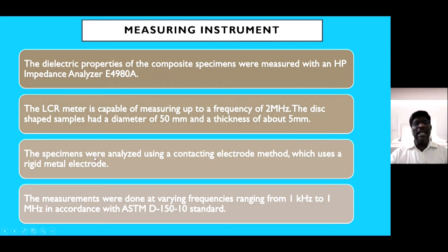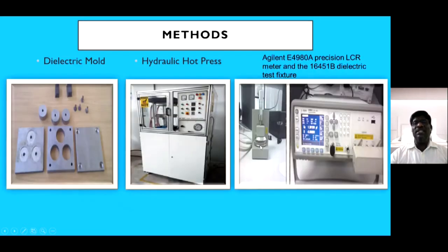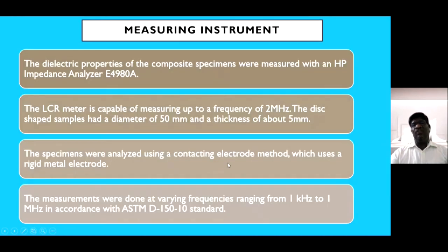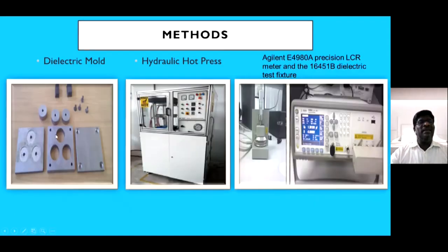The specimens were analyzed using the contacting electrode method. You can look at the picture. This is called the contacting electrode fixture. The diameter is 50 mm and the thickness is 5 mm. The contacting electrode method uses a rigid metal electrode. The measurements were done at varying frequencies ranging from 1 kHz to 1 MHz, or we can go from 1 kHz to 2 MHz also. We also follow a standard measuring method like the ASTM D150-10 standard for dielectric measurements, as well as standard dimensions for specimen preparation.